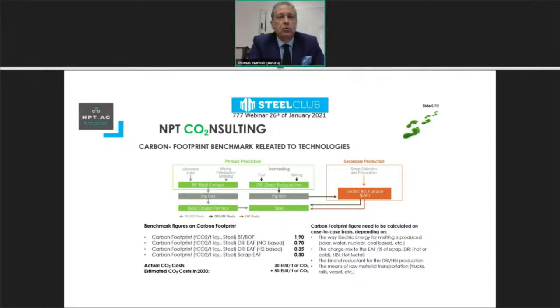If we see the traditional route of blast furnace, blast oxygen furnace, as we said before, it's on average about 1.8 to 1.9 tons of CO2 per ton of product produced. If we go to a natural gas-based DRI-EAF combination, we are around 0.6 to 0.7. If we go to a DRI-EAF combination with H2 as a reductant, we are at 0.3. And the carbon footprint of a scrap EAF is between 0.1 and 0.3.